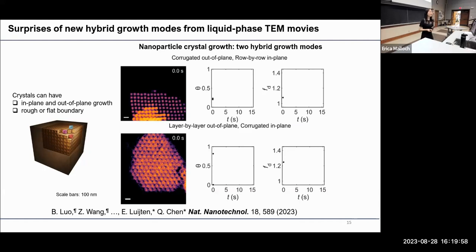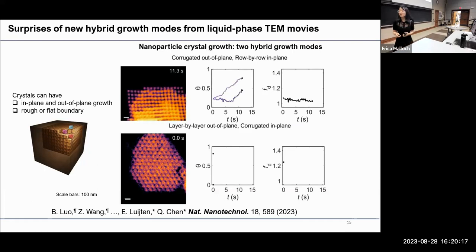I'm going to highlight the 2 hybrid growth modes. In those 2 movies, you're going to watch the particles of the same color, they are in the same layer. You can see in the first movie, the 3rd layer already started to grow when the 1st and 2nd layer are still growing. So that means out of plane, this is corrugated growth. But if you look at the boundary of each layer, it's actually pretty smooth. So in plane is row by row growth, which indicates it's a smooth boundary.